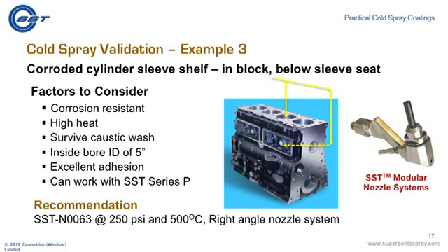So what we recommended in this particular case is use of our SST N0063 at the maximum pressure of the Series P gun, which is 250 psi, and the upper temperature limit of the manual gun, 500 degrees C, and a right angle nozzle system.